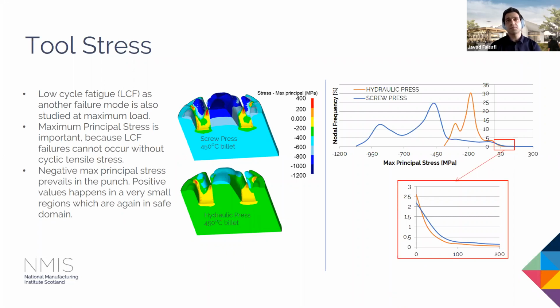Even though there might be some small areas experiencing positive, tensile stresses, we need to make sure that it is low enough. On the right-hand side, you can see the node frequency of maximum principal stress across the punch. And there is a tiny bit on the positive side, which is still lower than 200 megapascal, which is quite acceptable. And that was basically the study we carried out.